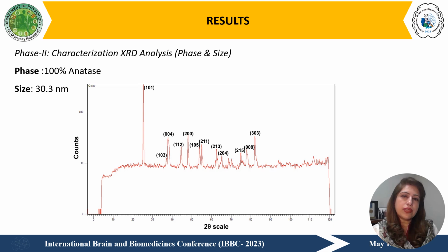Now let's talk about the second phase, where the characterization technique was carried out. X-ray diffraction pattern analysis was carried out to ascertain the phase and size of the titanium oxide nanoparticles formed by the jasmine flower extract. Now, here the titanium oxide nanoparticles synthesized by the jasmine flower were in 100% anatase phase, having the particle size of about 30.3 nanometer in size. And this is being indicated by the peak at the 101 degree centigrade, which is shown in this graph.